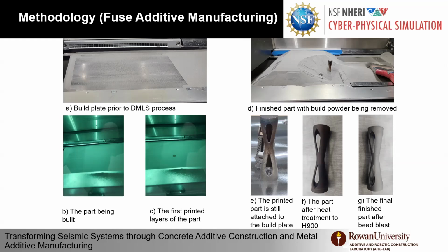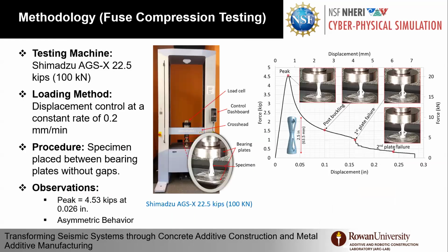The steel is stainless steel, and we tested that specimen at Rowan University using monotonic loading in compression to make sure that the behavior is stable after buckling. As you can see here, we achieved almost 4,500 pounds in compression. For this particular design, the double funnel, one funnel buckled before the other one. This is due to the imperfections that happened during the process.